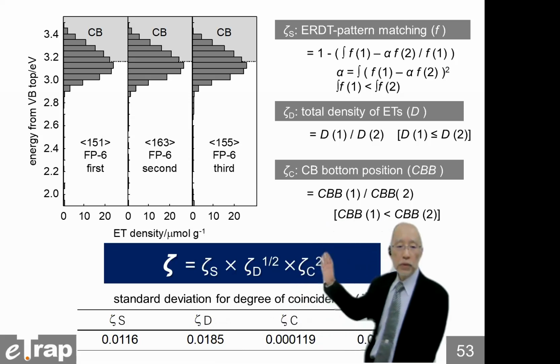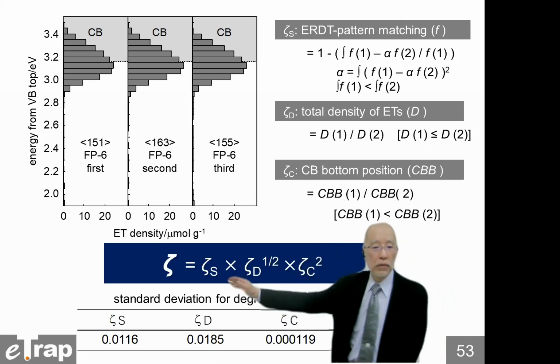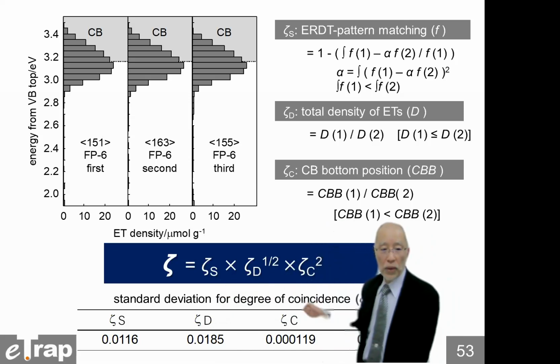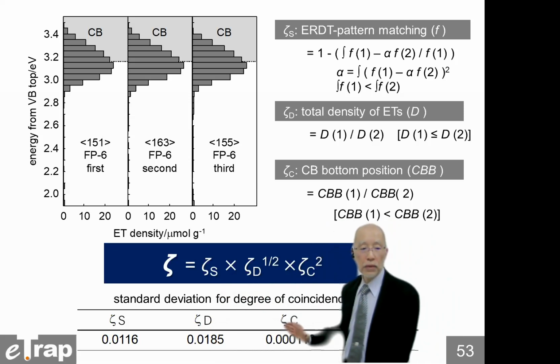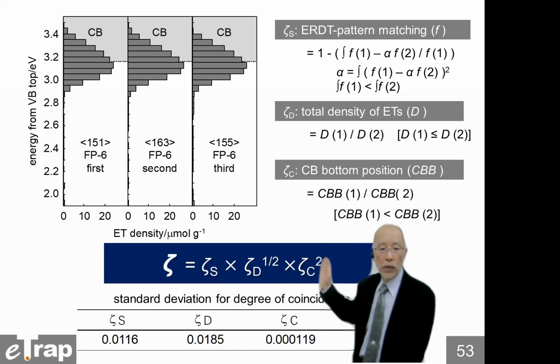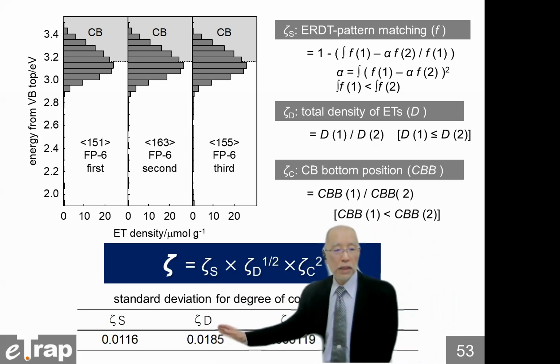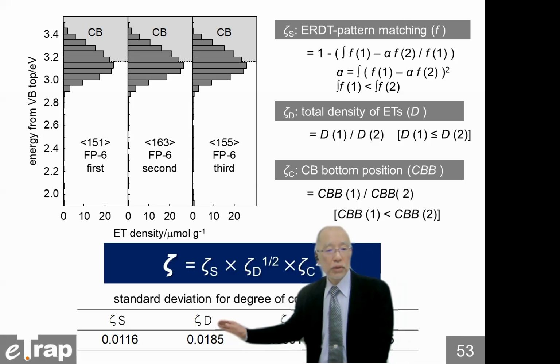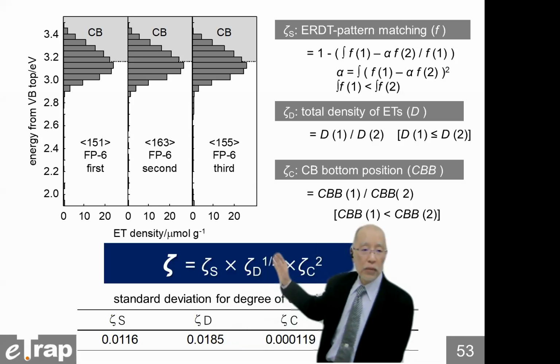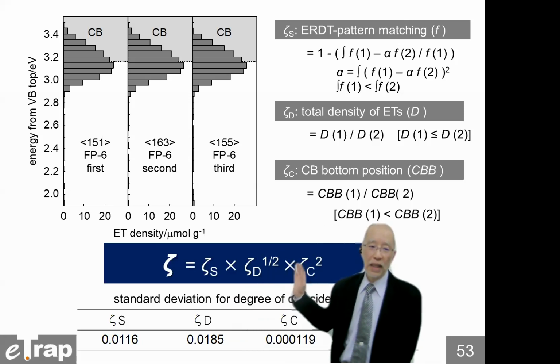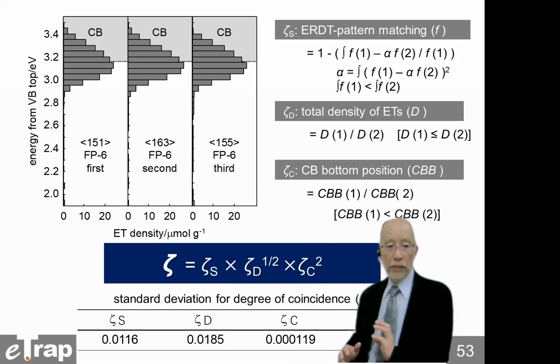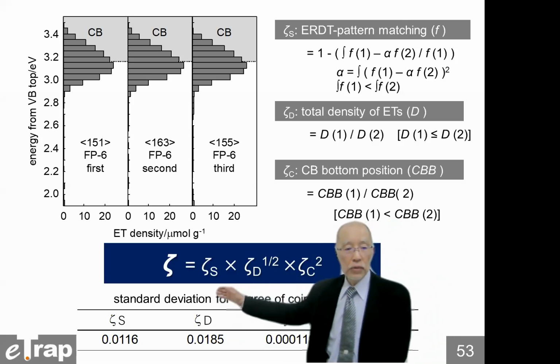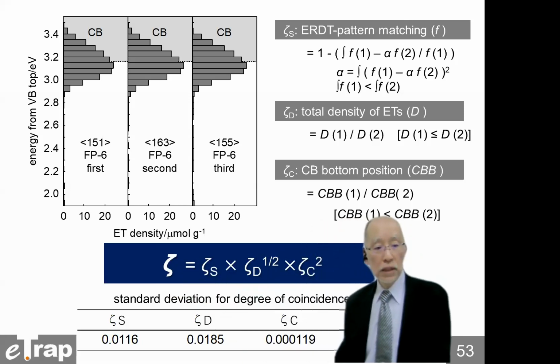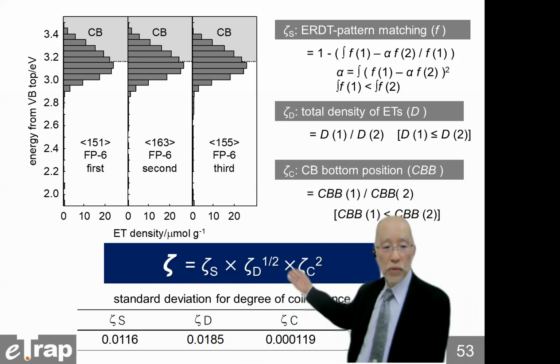So therefore, we put weight on multiplying those 3 degrees of coincidence. For small standard deviation, the degree of coincidence of CBB, we put a heavier weight. And for large standard deviation, the degree of coincidence of total density, we put a lighter weight. And this is just for convenience, tentatively determined, but we can calculate the total degree of coincidence of this ERDT-CBB pattern by multiplying those 3 partial degrees